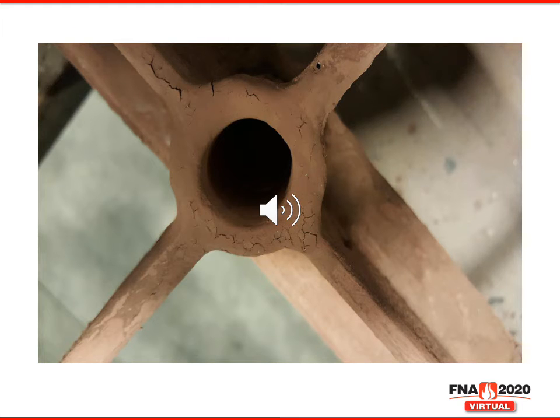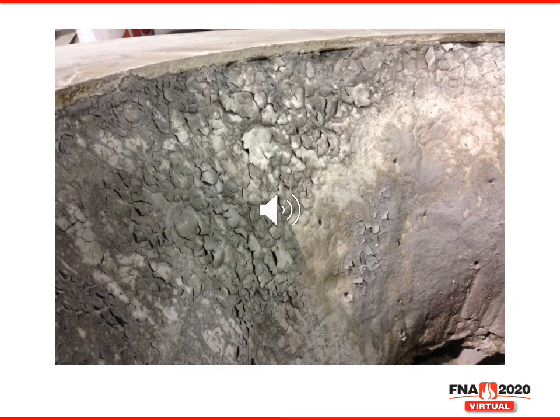In this slide, the photo shows the third coating failure or failure of coating layer. Here we can clearly see the shearing cracks developing due to the coatings being applied too thick. Once again, in this slide, the photo shows the third refractory failure or failure of the coating layer due to too thick of an application on a refractory substrate.